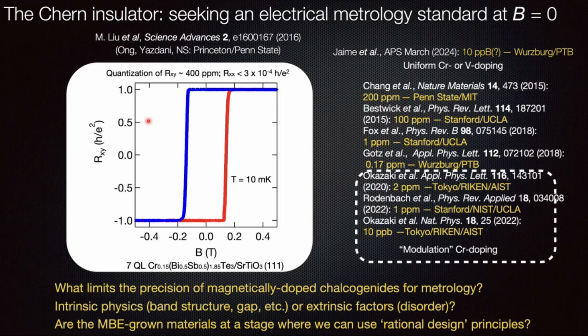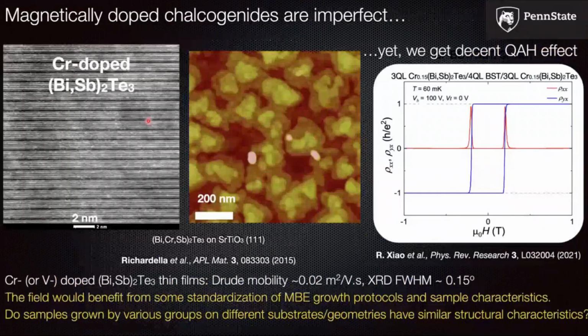So my question is, are MBE grown materials at a stage where we can go to a theory colleague and say, give me a rational design principle to make a sample which has a large energy gap, so that your topological states are protected, and you can get to the precision you need for your metrology experiments? My take is that the theory in this case is far from really helping us. All these nice ideas about scattering to this and that in terms of band structure, honestly, it doesn't work. I think Lawrence and I are probably one of only two MBE growers who will provide statements in slides like our samples are actually not that great.